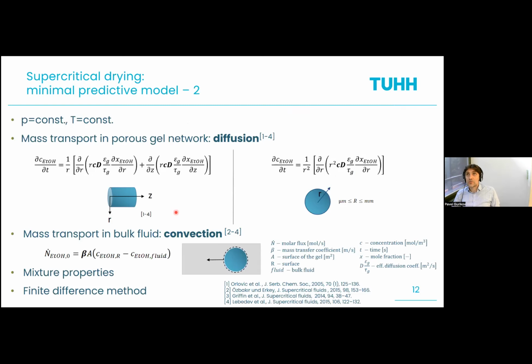Why does the diffusion approach intrinsically not work? Because, to explain it simply, the diffusion coefficient during supercritical drying is not constant. The flip side of supercritical fluids, contrary to conventional media, is that you can control pressure and temperature. In conventional media, like for example organic solvents, you only control temperature. But by varying pressure and temperature, you always have a very special type of behavior, and the diffusion coefficients, and also viscosity for example, are all functions of pressure and temperature, or we sometimes say density and temperature, or pressure and density, two independent variables. The diffusion coefficient, no matter what coordinates you're working in, is a function of these process parameters, and you have to take it into account.